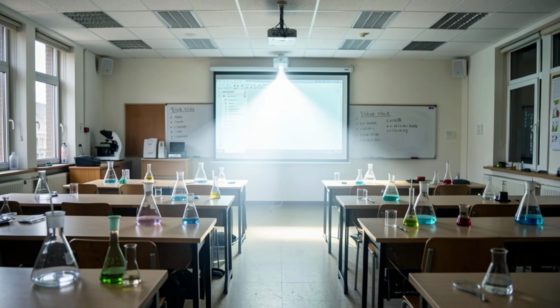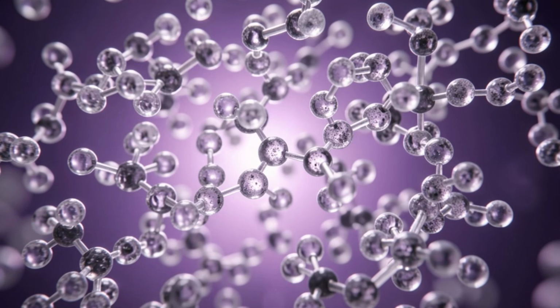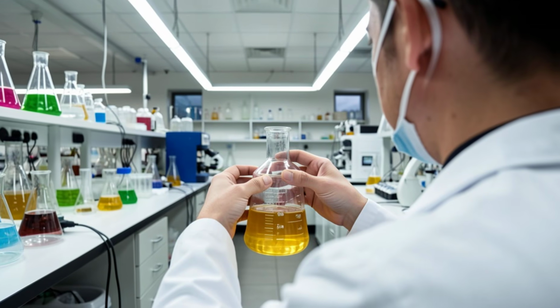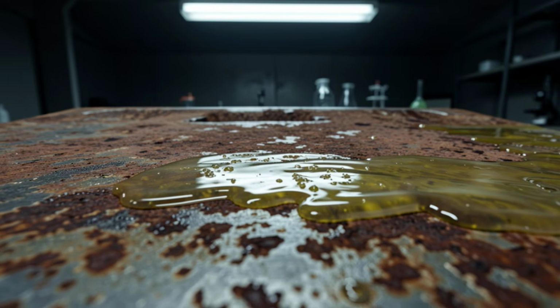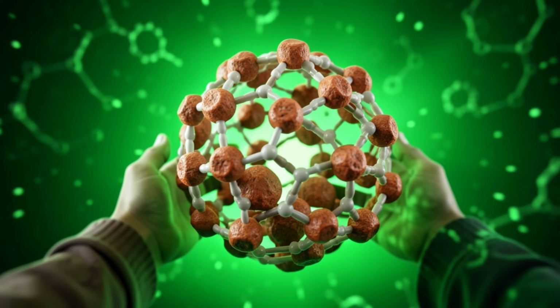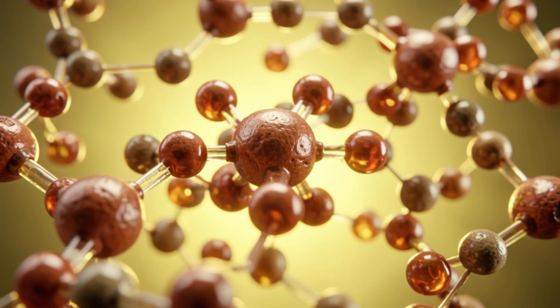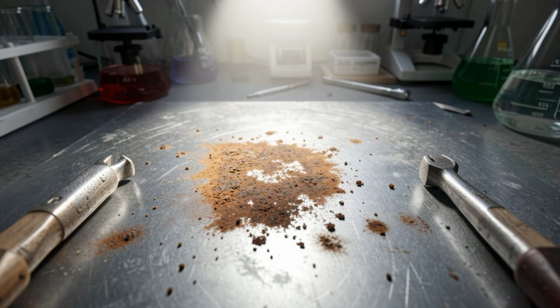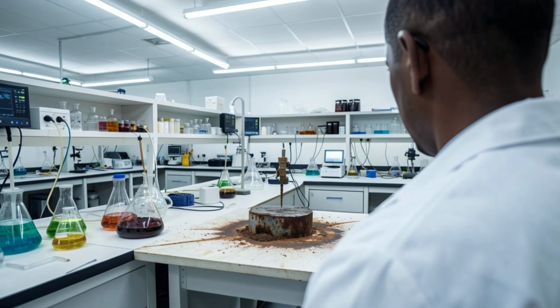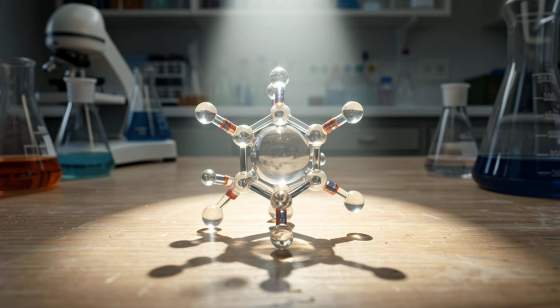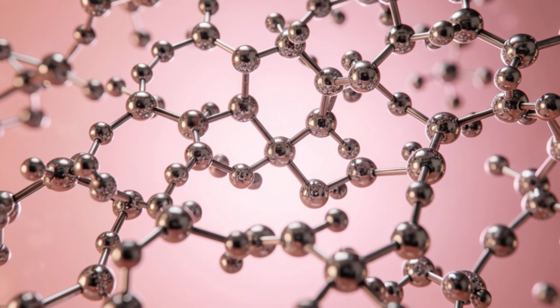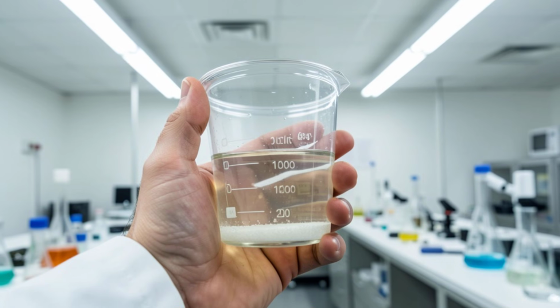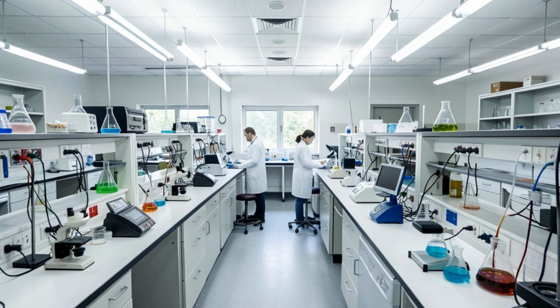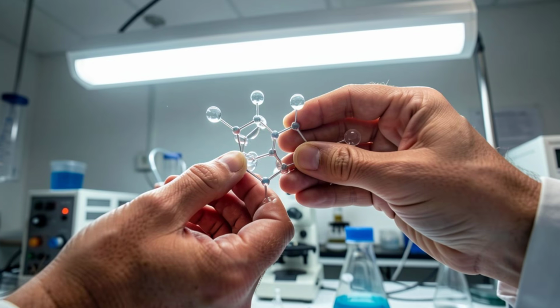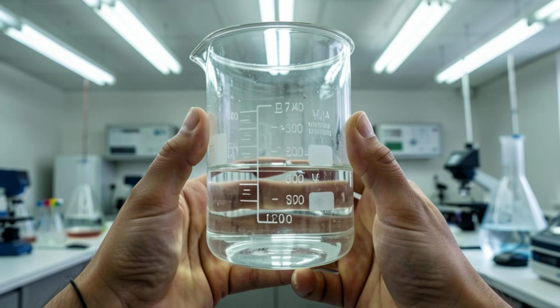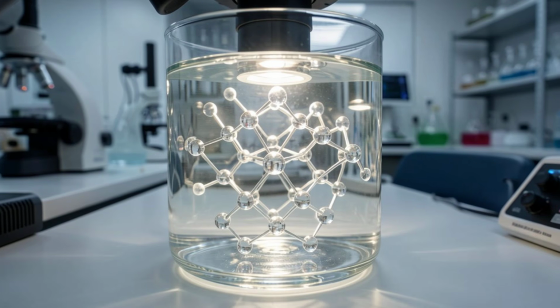Chelation comes from the Greek word for claw, and it is a precise description of what happens at the molecular level. Citric acid is a weak organic triprotic acid, meaning it has 3 acidic hydrogen groups that can release and interact with metal ions in solution. When citric acid dissolves in water, its molecules form a specific geometric shape that allows them to wrap around ferric iron ions, the iron that is bonded with oxygen to form rust, and bind to them through multiple attachment points simultaneously. Those claws lock onto the ferric iron, pull it away from the oxide structure, and hold it in solution as a stable water-soluble complex.